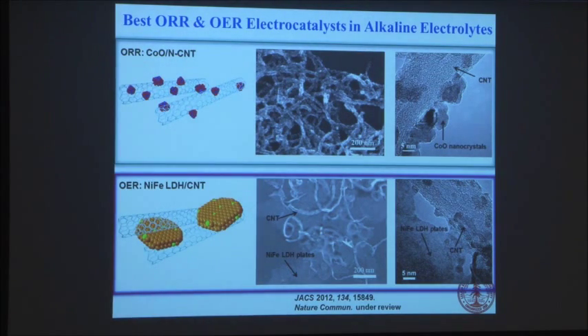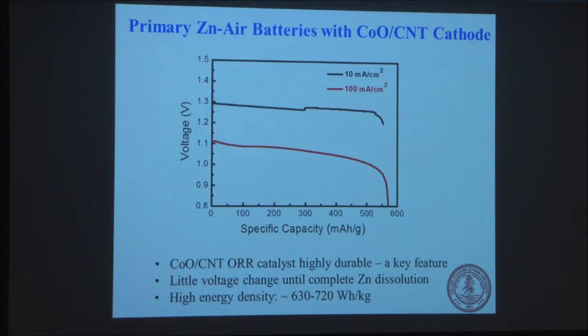So we're using two materials for the battery right now. One is the cobalt, as I mentioned, for oxygen reduction. And this is a piece of new data that is still being reviewed. It's a nickel iron layered double hydroxide. Okay, it's very thin plates that are made on nanotubes. And this turns out to be the best OER catalyst that we can make. Anyway, and then we combine these two for the zinc air battery, and this is the primary battery.